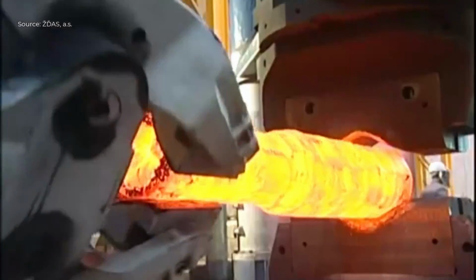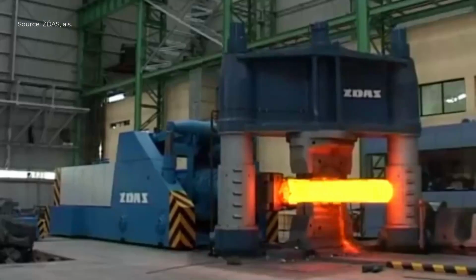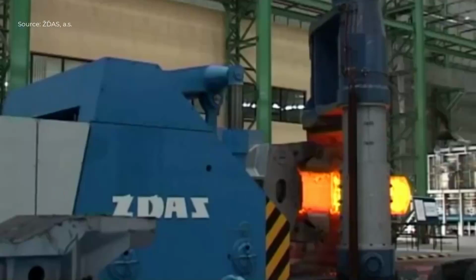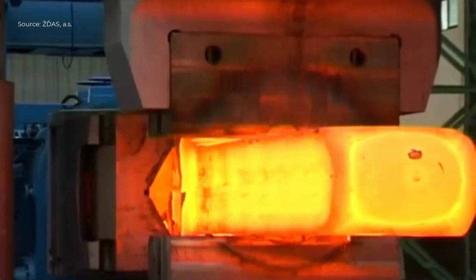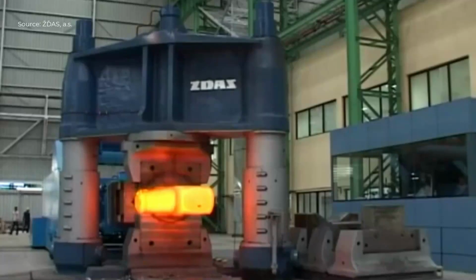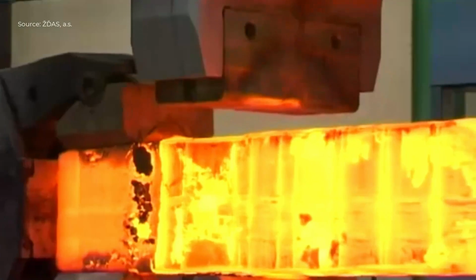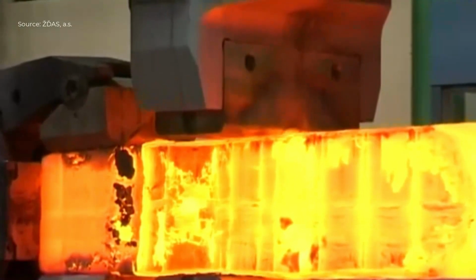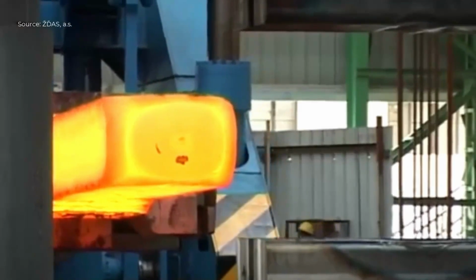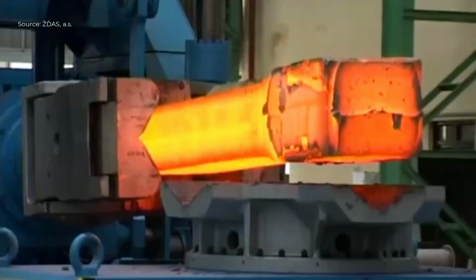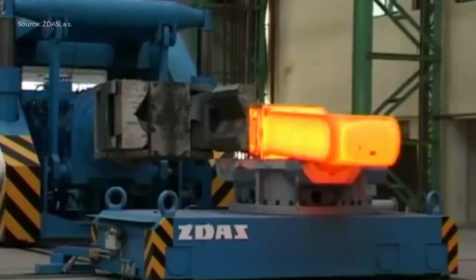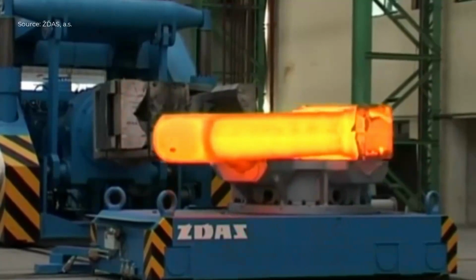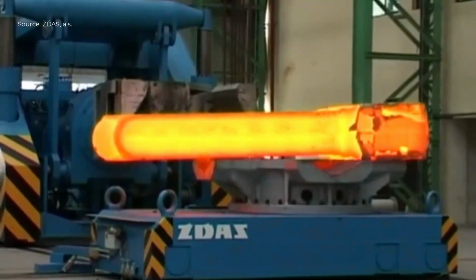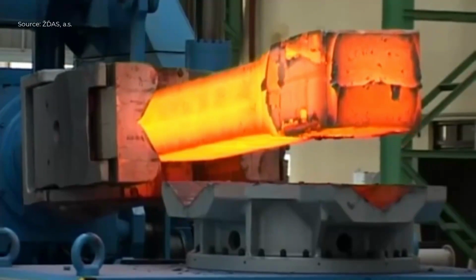Process with the CKW4000 hydraulic press begins with positioning a preheated metal ingot or billet onto the forging plate. This press utilizes a pull-down, two-column design where the press cylinders are mounted on a stationary middle cross girder. These cylinders act downward on the lower cross beam of a movable frame, pulling the upper anvil toward the workpiece. The material is then subjected to controlled deformation through open die forging operations, such as upsetting, piercing, drawing, or ring forming.